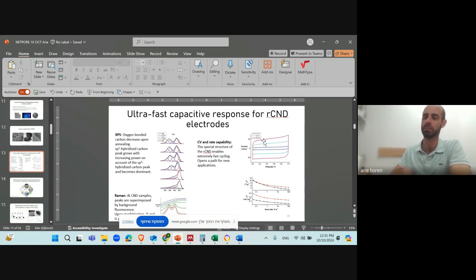Where you see a redox, it is like spectroscopy. You scan the potentials, and whatever potential that you have any redox reaction, you will have very high current, positive or negative current. Here we see the scan of potential. We don't see any peak, and the reason is there is absolutely no redox reaction. And why is that? Because we are left with only graphitic carbon. It is inert electrochemically, so we don't see any peaks.